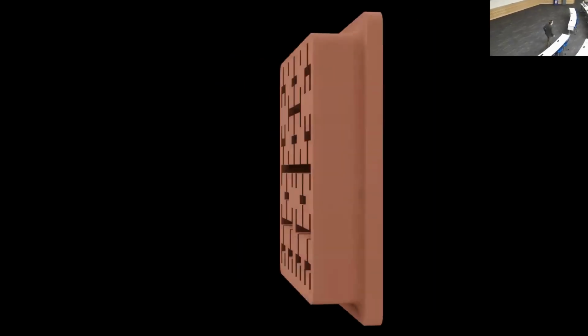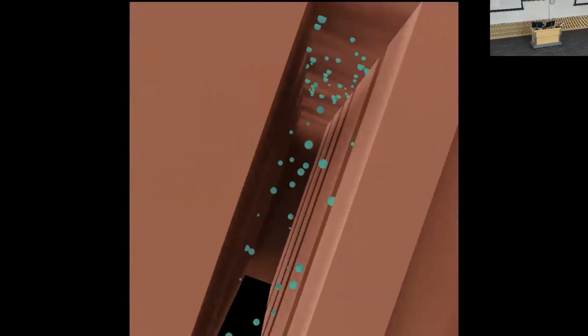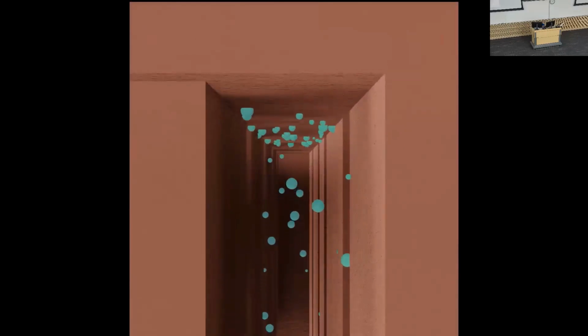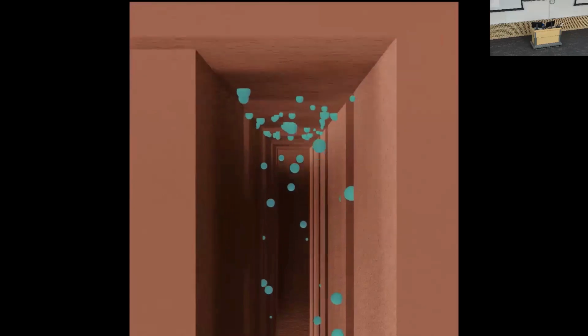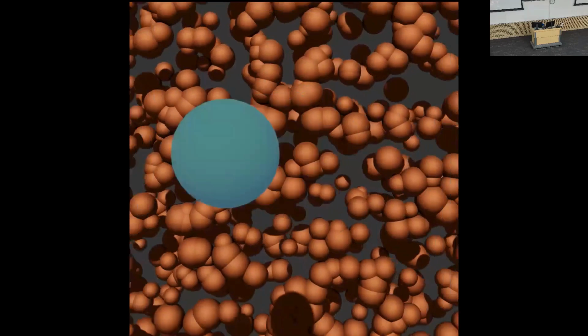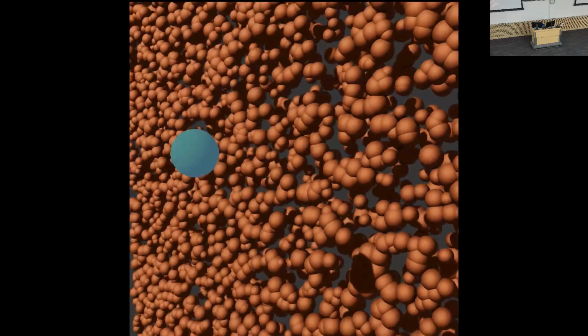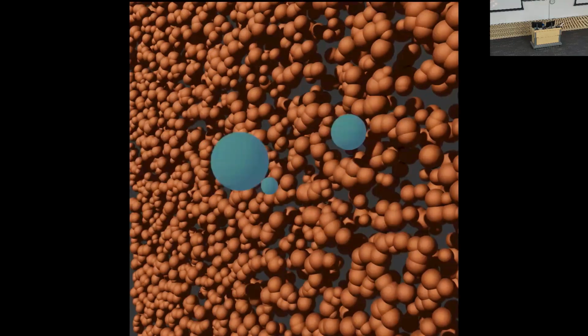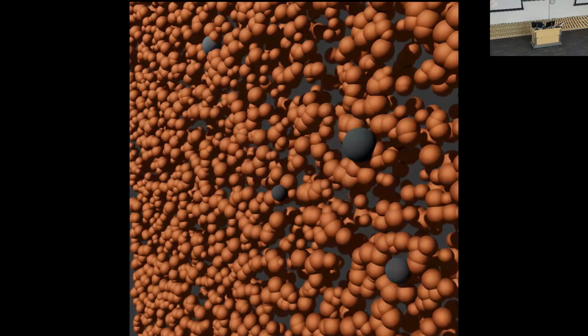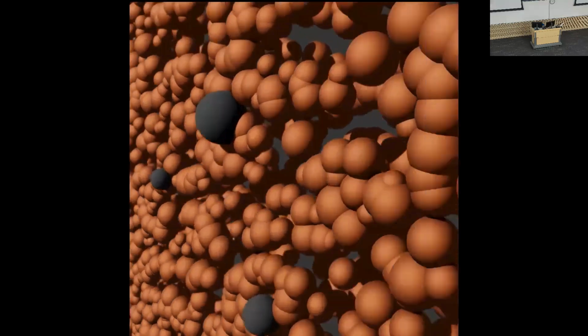Our idea was to build a filter that is made out of metal that you don't throw away, that is self-sterilizing. So we're using copper here. We're using high surface area material by making all these channels that is thin, and we make them porous because binder jetting is porous already, right? So we don't need to worry about densification anymore. We now keep it porous. And once a droplet with COVID-19 hits copper, it would die within 10, 15 minutes, right? So copper is very antiviral, antibacterial.